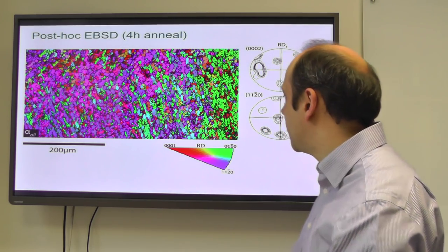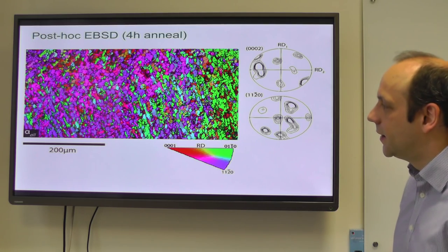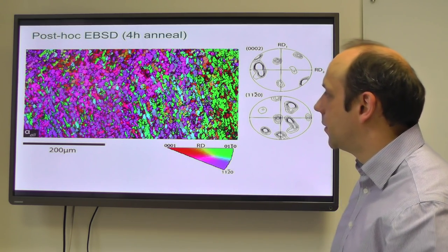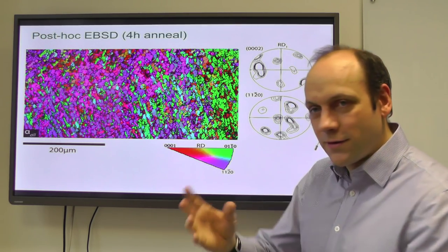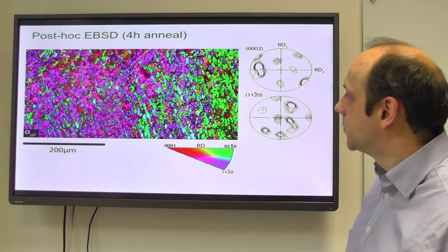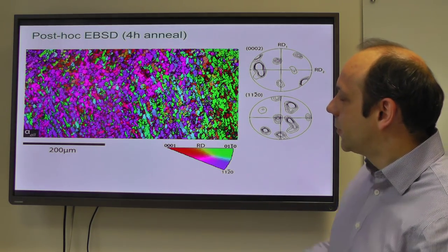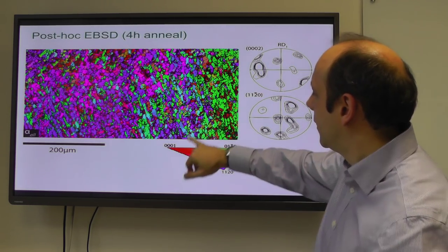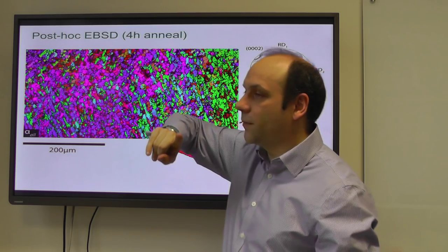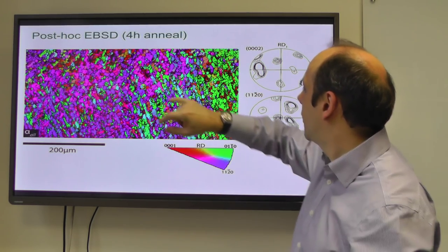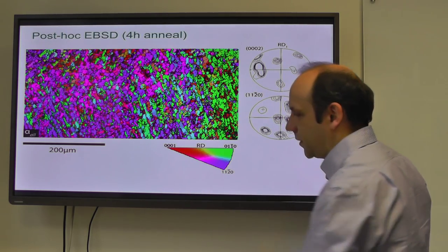The way you measure orientations is by electron backscatter diffraction (EBSD). Here's such a map where the colour shows the orientation of the crystal - individual primary alpha grains are visible. The colonies of lamellar alpha all appear as one colour. The black dots are the beta phase - we're just picking up the primary alpha here. The colour key means: red indicates 0001 pointing out of the page, blue indicates 11-bar-20 pointing out of the page, green indicates 01-1-bar-0 pointing out of the page, and purple is somewhere between the prism and basal plane.